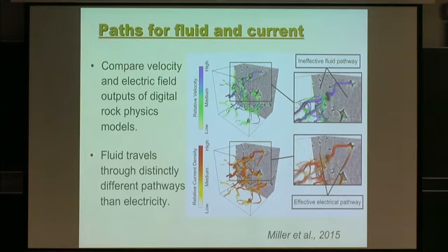But what you see is even though there is a melt conduit, for permeability it doesn't contribute much at all, whereas for conductivity it does, all right? So I'm just zooming in and these features are everywhere, okay? What's the melt fraction? In this case, it's 5%, all right?